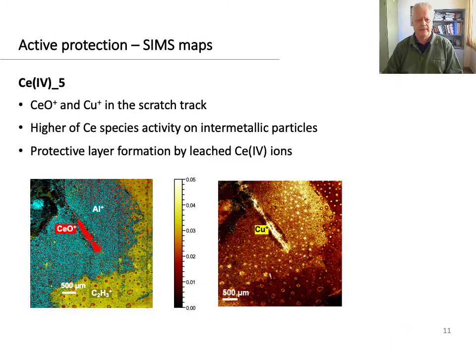cerium-4-5 coating. Now, clear evidence for the presence of cerium oxides in the scratch track was obtained by ToF-SIMS surface maps. After 7 days of salt spray test, an accumulation of cerium oxide and copper species was found within the scratch track, confirming the high reactivity of cerium species at intermetallic particles, forming a protective layer of insoluble species.